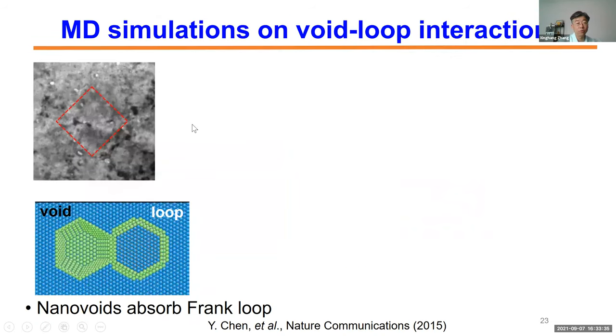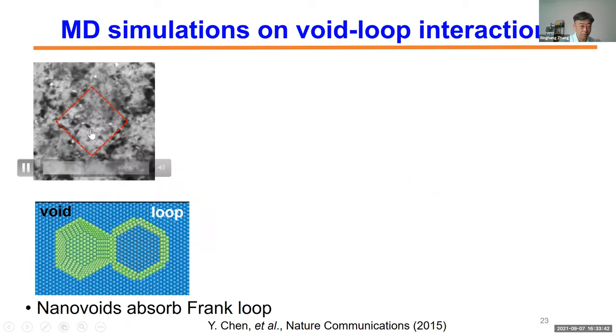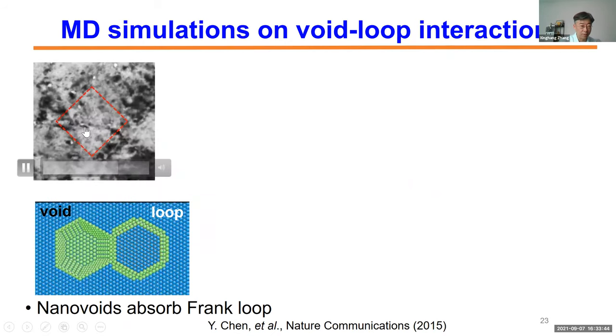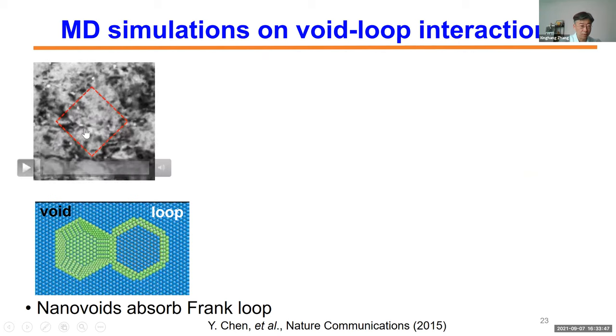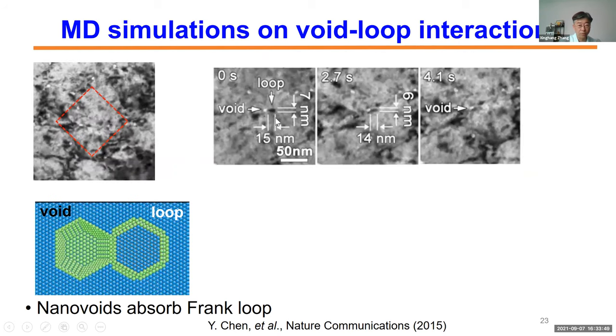So then I'm going to show you this zoom-in view of in-situ irradiation for nano-twinned copper. Notice in the red box, there's a black defect clinging to the white voids, and it was being gradually sucked into that little void right there. So this is measuring the dimension of these black defects, and it happens to be right next to the void. That is an interesting phenomenon. And so we hypothesize that if this is an interstitial loop, they might fill in the void.